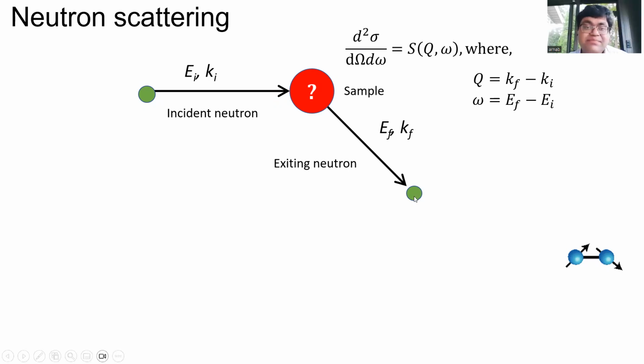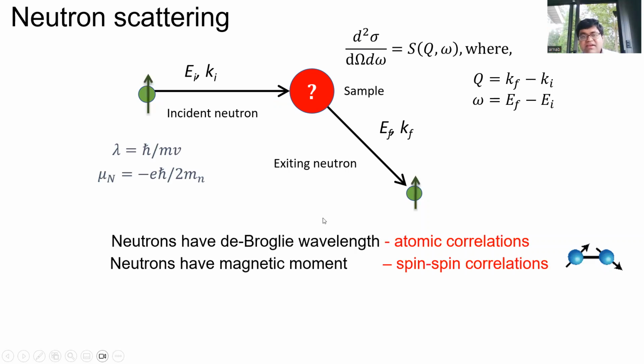In neutron scattering, what happens is that you have an incident neutron with an incident energy and momentum. It gets scattered from a sample, and you get an exiting energy and momentum. So the overall momentum transfer is given by the difference of the initial and final momentum. The overall energy transfer is given by the difference of the initial and final energies. Now, as it turns out, neutrons have two properties. One is that they have a mass, and they have a de Broglie wavelength. And because of that, you can actually look at the atomic correlations.